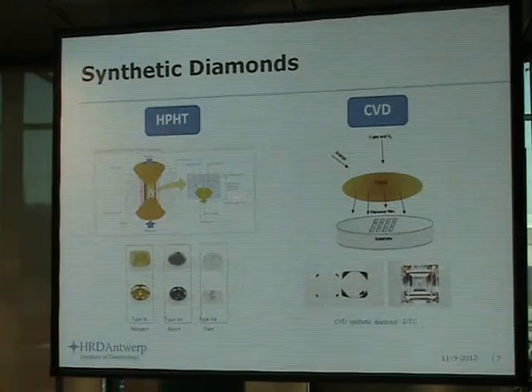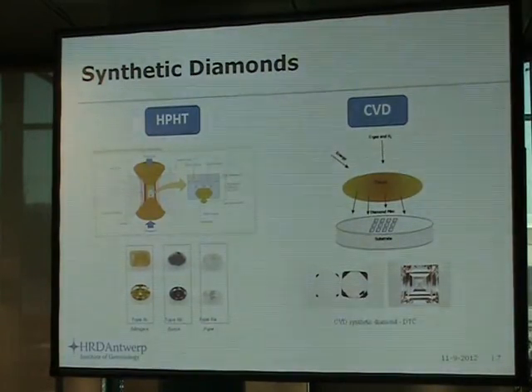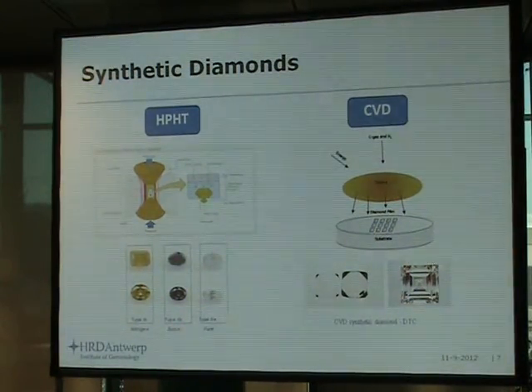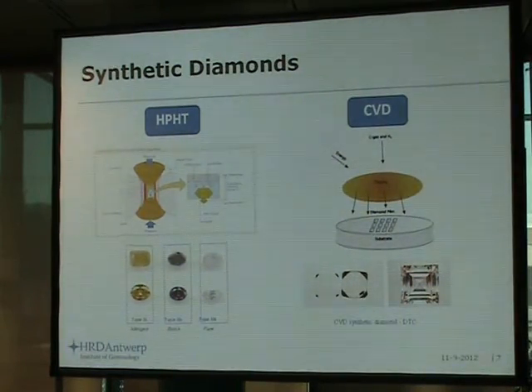Producing most of the time yellow colors, because there is a natural nitrogen abundancy in the atmosphere. If you add special products, additives like boron in the growth atmosphere or environment, then you achieve blue diamonds. If you add so-called nitrogen getters like titanium, aluminium, and comparable, which is a very complex, tedious process, then one can achieve colorless diamonds.